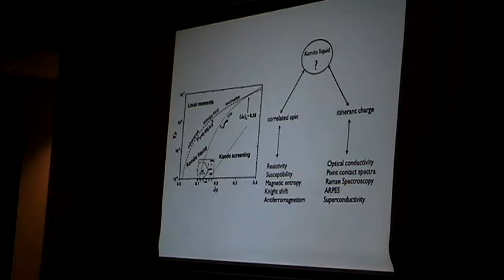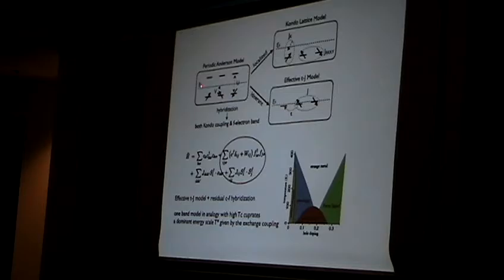There are important implications of this two-fluid model. It changes our understanding of quantum critical properties. For example, like resistivity, the two-fluid model predicts linear temperature behavior, while sublinear behavior was thought to be a signature for quantum criticality. The question is: in this model, is this accidental or does it also have some fundamental origin? This is something which we really need to clarify.